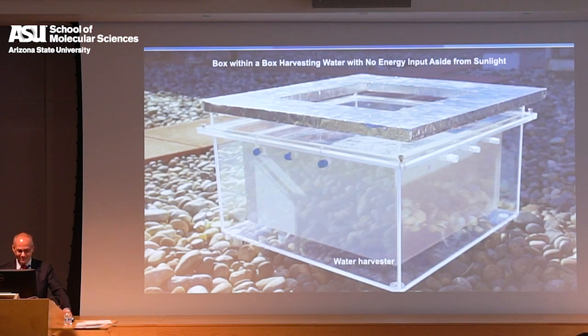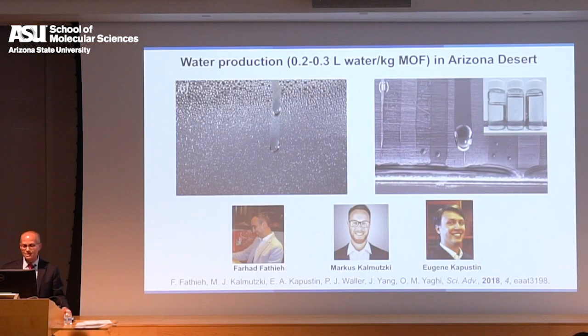Okay, so ultimately, I didn't tell you, Betty, but I called the students up at 2 o'clock in the morning and they said, oh, the experiment is not working. We see that because they have probes into the MOF and everything, we see that the MOF is getting saturated with water, and we see it coming out as vapor, but it doesn't condense. I said, just put it under the ground. Put part of it under the ground, and the dirt is probably 2 degrees, 3 degrees lower in temperature than the rest of the device. It should condense. And indeed, then that worked, right? So it pays to call your students at 2 o'clock in the morning.